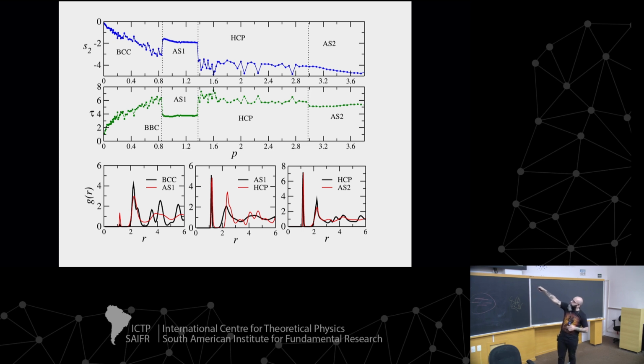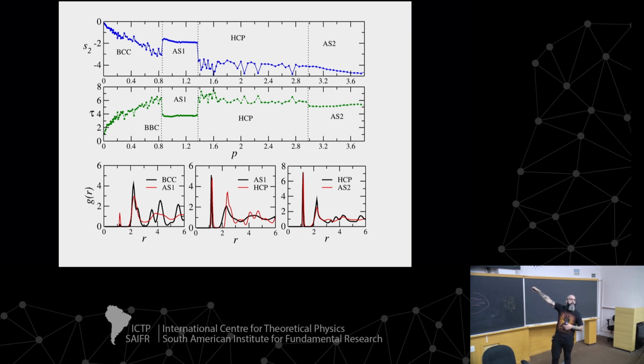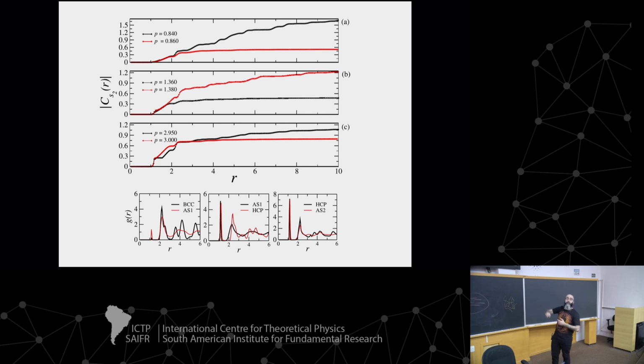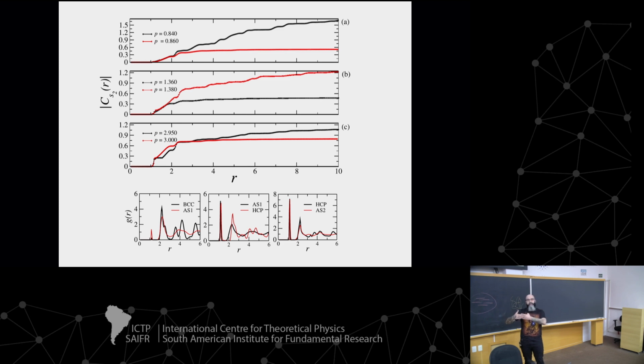And it's funny because if you look at the HCP and the second amorphous region, the g(r) at short range are really, really similar, but they are different at longer range. So we have to understand what happens in this longer range. And to understand this, we evaluate the cumulant of the entropy. As the name says, we are accumulating the entropy as we go to a further distance.